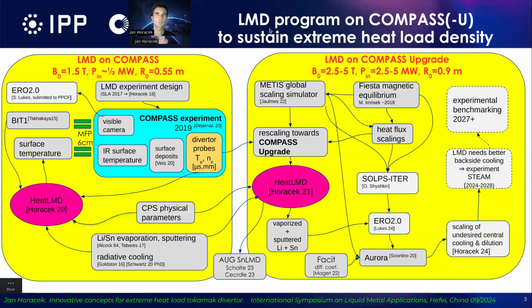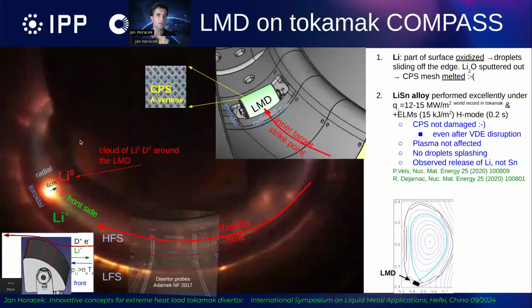We developed a program on COMPASS to sustain extreme heat loads with liquid metals. So we started in 2018, where I published this paper on HEAT LMD simulations. Then we did the experiment itself in 2019, and then we measured the infrared camera surface temperature and compared it with the output from the HEAT LMD model. And it was very well comparable, which means that the heat conduction inside the target is the most dominant part, and that the lithium vapor shielding was pretty negligible in this case, unfortunately, because then we could not really quantify it. But then comparison of the visible camera with the BIT1 code showed also nice correspondence of a 6 centimeter large cloud of radiating plasma, because that's the mean free path of it.